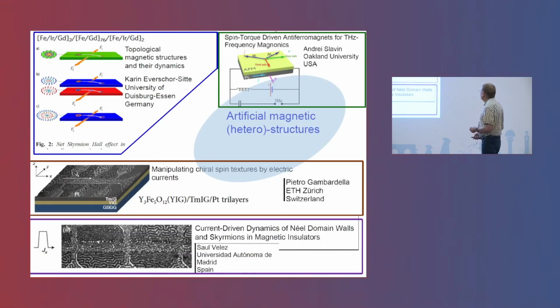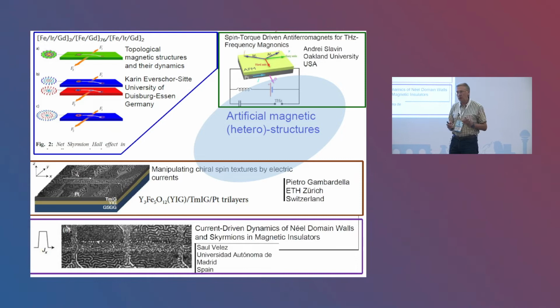So now coming back to the artificial magnetic heterostructures, skyrmions were omnipresent at this conference. In one form or another, in most of the talks, skyrmions or other topological magnetic structures were present and discussed. And there was an interesting visible trend in these presentations focusing on manipulation and control of these topological spin objects with electrical current in the multilayer structures composed of the ferromagnetic material where skyrmions or, say, domain walls or magnetic bubbles could be generated and manipulated by the currents which run through the deposited, say, metallic layer or stripes with strong spin-orbit coupling, like, for instance, platinum.